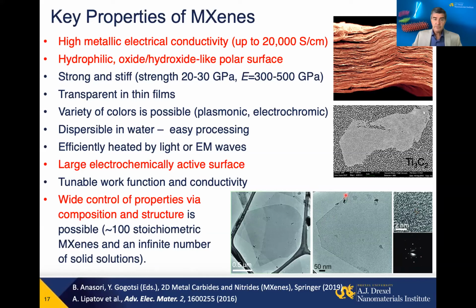But one thing you may notice is that they're much more rigid. So you can have a hanging film over a hole in a grid without support and it will hang. Graphene won't; it is flimsy and collapses. The reason is the couple of atoms in the structure, giving much higher rigidity and also very high mechanical strength. That's why by solution processing we can make flakes which go up to 20-30 microns, and we cannot make the same with molybdenum disulfide, for example. It doesn't have sufficient strength.